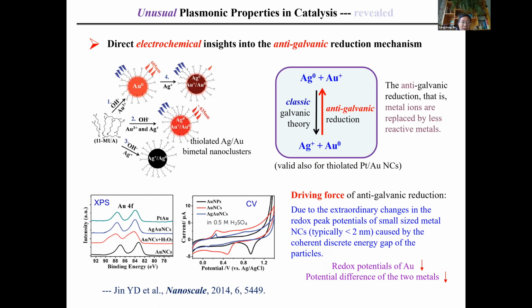By systematic XPS and CV study, we gain direct electrochemical insight into the mechanism. So the driving force of anti-galvanic reduction was found to be due to the extraordinary change in the redox peak potentials of small-sized metal nanocrystals, typically smaller than 2 nanometers, caused by the coherent discrete energy gap of the particle.